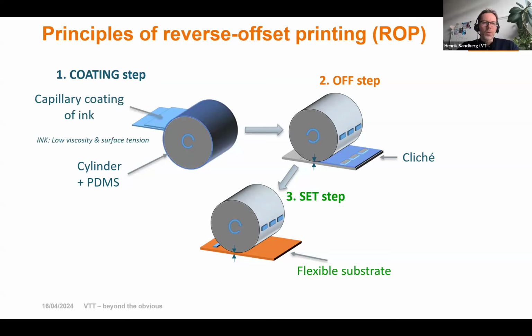So we use a capillary coating system for the PDMS coating, and this requires low viscosity and surface tension of the ink, and the ink optimization, of course, is also important. And we don't do that too much in-house alone, but we do it together with partners.